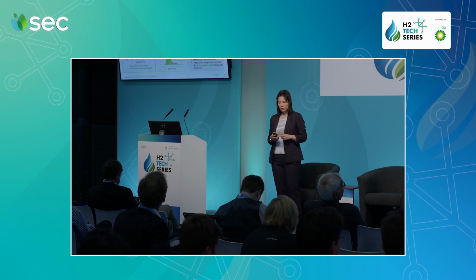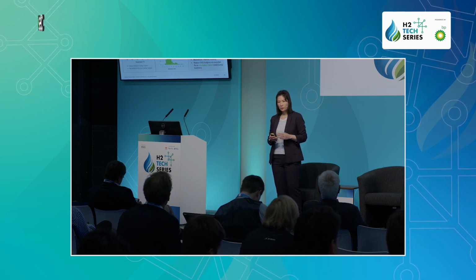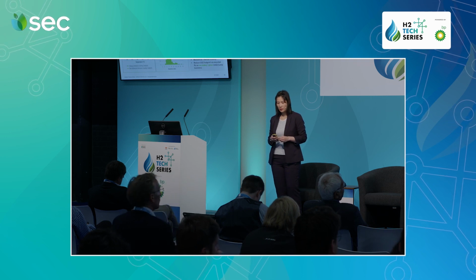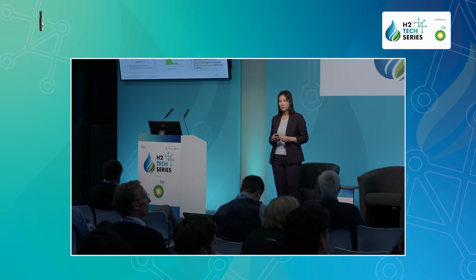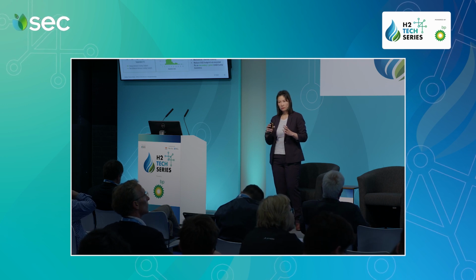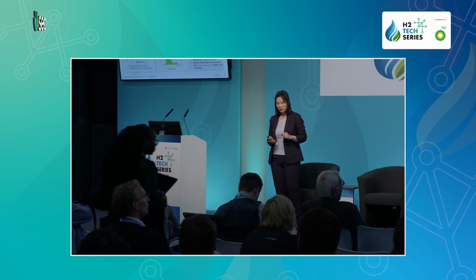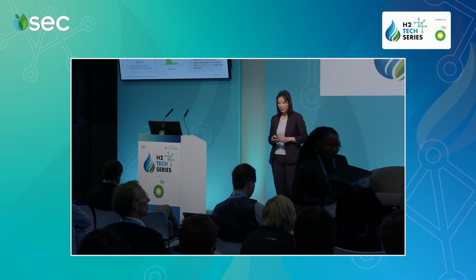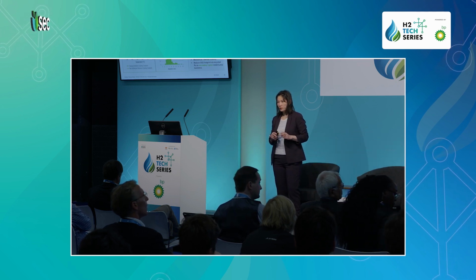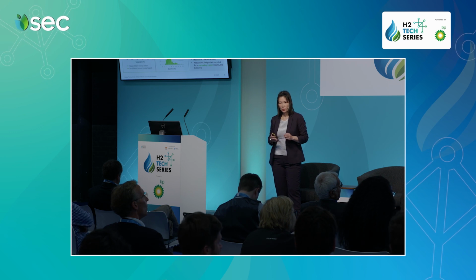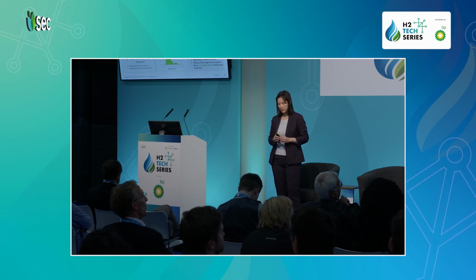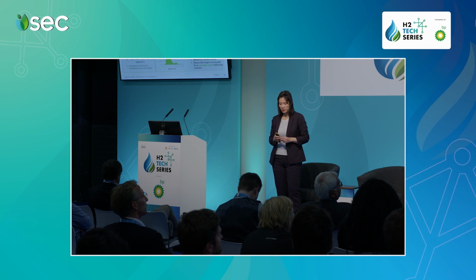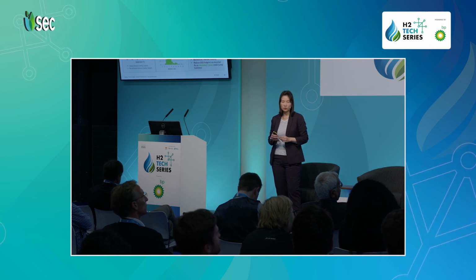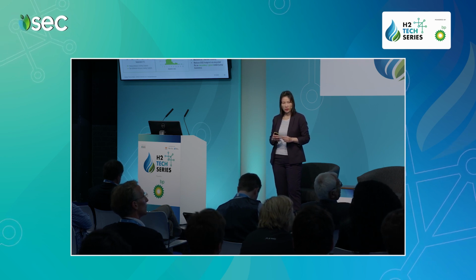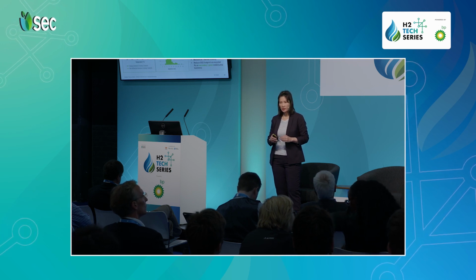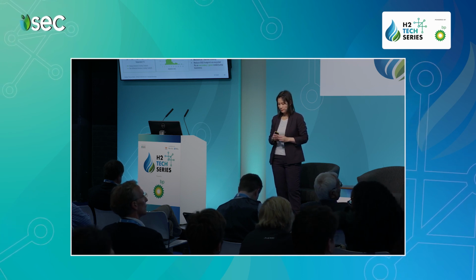Two factors are very important for the performance. The first one is how to coat the active material on a suitable carrier. You can see this is a half sphere. The black shell is the active material, well distributed on the carrier. The second factor is metal particle size. We have a technology to control the particle size within a limited range.